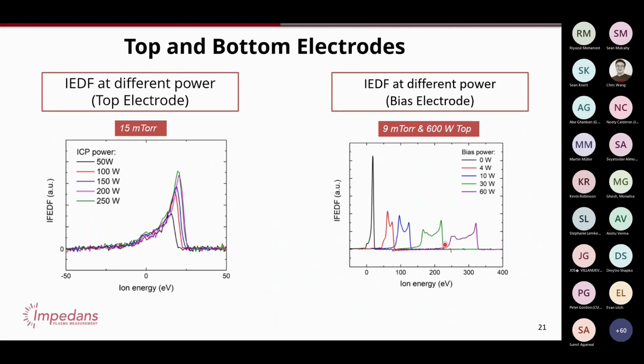Yeah, this is also where pulse plasmas come in. Especially in a CCP tool, things are more coupled, so you can't independently control the top and bottom in a CCP. You have changes in ion flux and ion energy with power in a dramatic way. But with pulsed RF, it's quite important because by changing the duty cycle, you're changing what the average energy is.